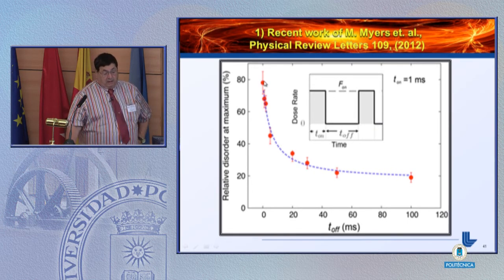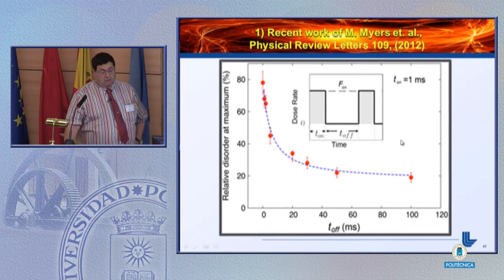And here's a plot now. So these are all for the same dose, but with the time off being varied. And lo and behold, he gets a beautiful second-order kinetic curve, from which he extracts a number that turns out to be about 4 or 5 milliseconds, which is essentially what's called the dynamic annealing effect. So what he's done here is, over 2 orders of magnitude, he's been able to measure the kinetics associated with the interpulse relaxation.